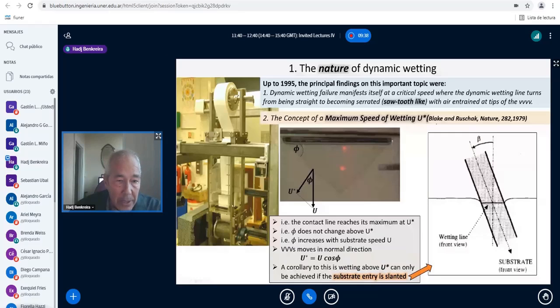line is normally straight, it turns into a V shape. So you'll have almost like a sawtooth. And at the tip of the saw teeth, you will have air entrainment. So imagine, normally, I can't play this movie unfortunately, imagine the dynamic wetting line is straight, but then above the air entrainment speed, you will have a series of V's, and then at the end, you will have air being taken in at the tip of these V's.